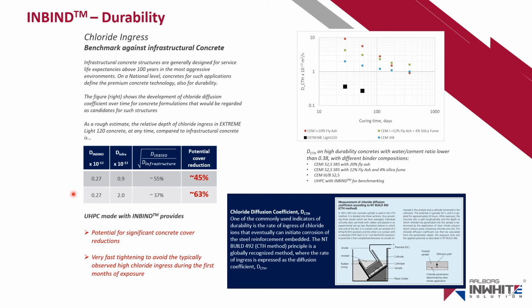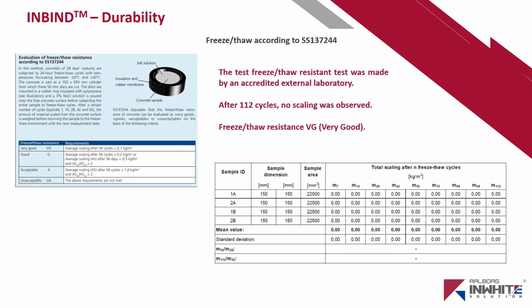The chloride diffusion coefficient was equal to 0.27 times 10 to the negative 12, while for traditional infrastructural concrete it will be between 0.9 and 2. Such a small value could lead to a potential cover reduction between 45 and 63%, which is a very promising result in terms of material savings.